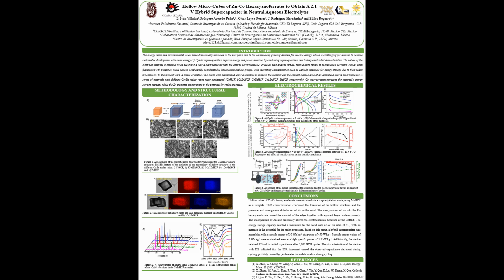charged state. The equivalent electrical circuit involves components representing the electrode's contribution to the hybrid device's impedance behavior. The negative electrode on the left side is the carbon, where the diffusion part is not present in the equivalent circuit. The right side shows the contribution of the positive electrode, cobalt zinc Prussian blue analogs, which includes the diffusion of the charge-compensating ions inside the solid.